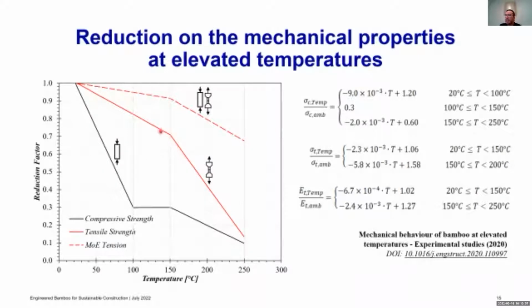Below 100 degrees in compression, you start softening the fibers, but after 100 degrees there is a section where there is not much change, because you're losing all the moisture content, and you can even increase the strain slightly after this point. But then after 150, which is where we found that bamboo starts to pyrolyze, the decrease is huge.